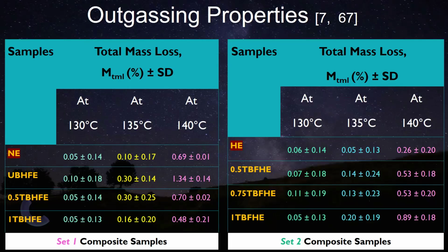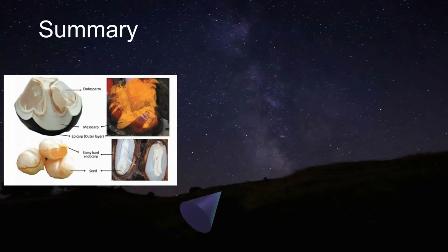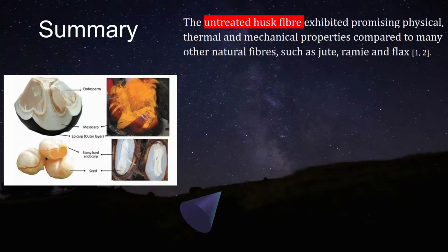So it was expected, but I suggested that if we have better equipment, considering the fact that we have the limitation over here, we need to redo that one. But this is a convincing result we got. The total mass loss was below 1%, even though we baked or prepared the sample in a normal condition. So yes, after all those things, the summary we came up with is actually the ending portion, I can say.